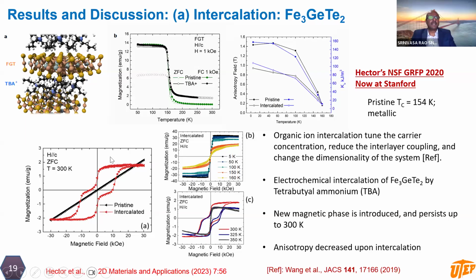The one that caught our attention particularly, I would like to draw your attention to this particular figure. You see, in the pristine case, this compound is a paramagnet at room temperature. Upon intercalation, you see the magnetic behavior of this compound changed, and you see hysteretic behavior, which is absent in the pristine case. And even within the hysteretic behavior, you see a step-like feature. That means that you have another ferromagnetic phase that is created after this compound is intercalated with the TBA plus.